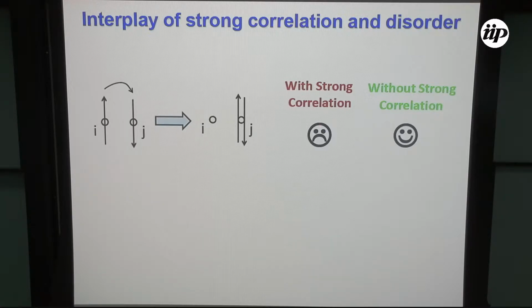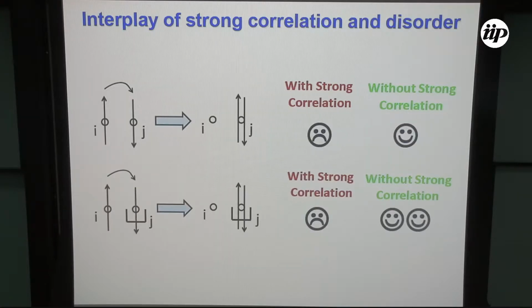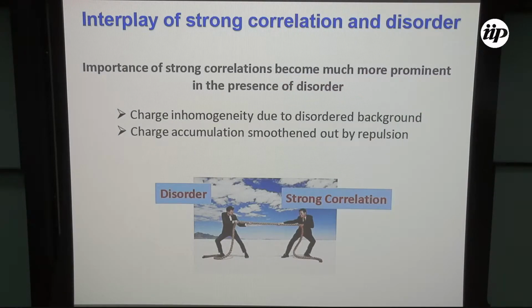It's a happy hopping. Now let's introduce disorder in this problem. Let me show you schematically. Suppose you have an attractive potential on the jth site. So this electron will now want to hop here. This is a happy hopping if you don't have strong correlation, because you are going from a higher potential to a lower potential. But with strong correlation, it's anyway blocked because you don't want double occupancies. So what it shows is that the effect of strong correlation becomes much more prominent if you have disorder